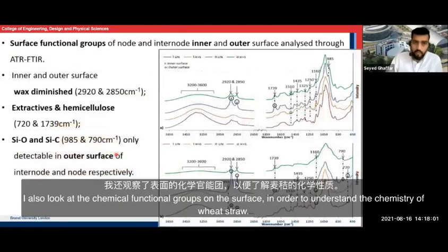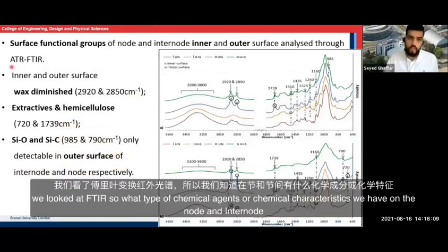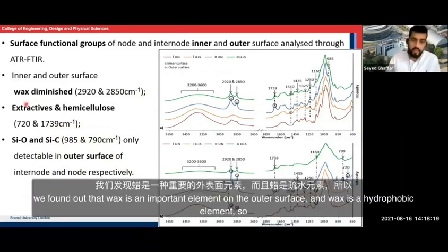I also looked at the chemical functional groups on the surface in order to understand the chemistry of wheat straw. We looked at FTIR, so what type of chemical agents or chemical characteristics we have on the node and internode. We found out that wax is an important element on the outer surface, and wax is a hydrophobic element.